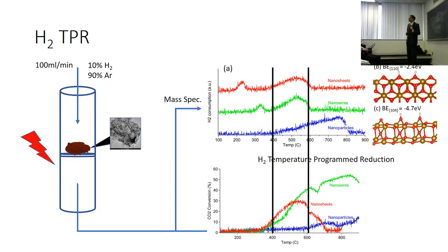Actually, counterintuitively, hydrogen adsorbs stronger to the 104. You'd expect the 104 to be more reactive, and that's not what we're seeing here. So it's not a facet thing, it's that the sites of the material are different in some way, perhaps because of the shape or nanostructure.